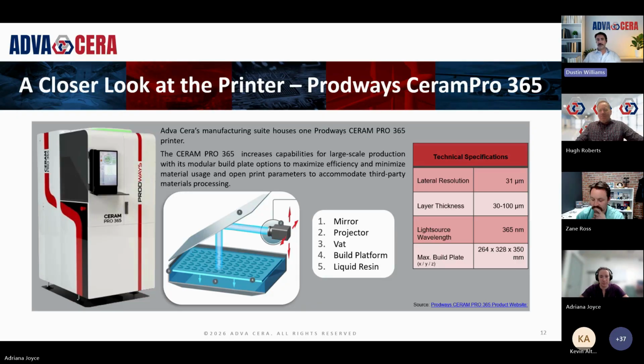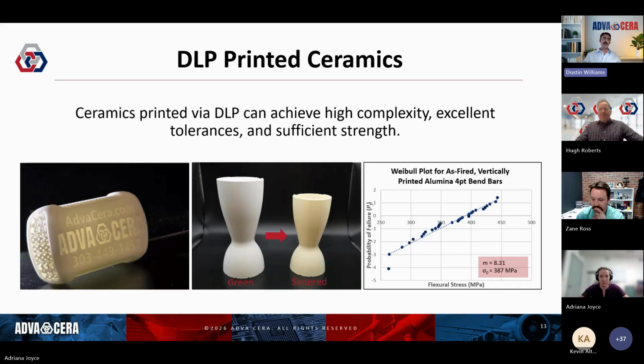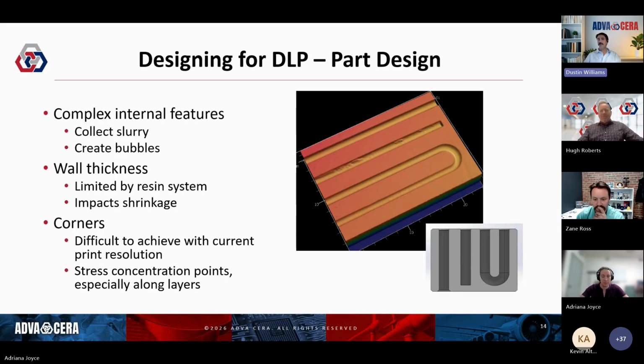We have created structures 200 microns or less, but you've got to think about the surrounding structure. So that is going to be very design dependent. We have that resolution of 40 and 31 microns between the two printers. That doesn't necessarily mean we can print a 40 micron wall on a part. So it's going to be very design dependent, and the best is just submit your design or submit your idea for a design to us, and we can chat through that. Did you have anything to add? Yeah, if you don't mind.